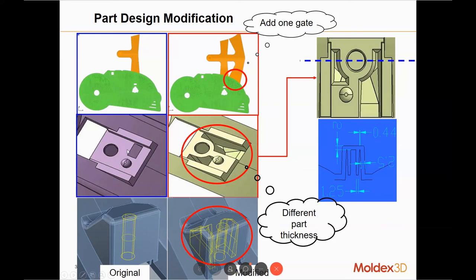So as we can see in the dimension page, the part dimension actually ranges from 2.5 millimeter to 14 millimeter. So actually in this small region, originally there was some thickness difference. And with this modification, the thickness becomes more even, so that the melt will not fill the bottom region first and create a closed loop on top. Once they change this part thickness, the melt will be able to flow through the whole region evenly from the right to left.